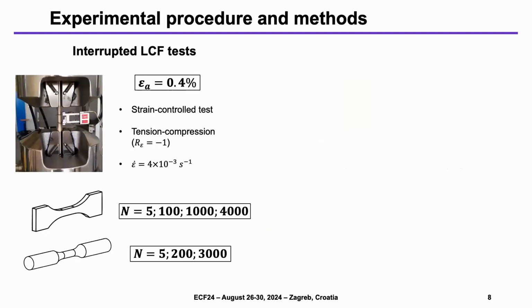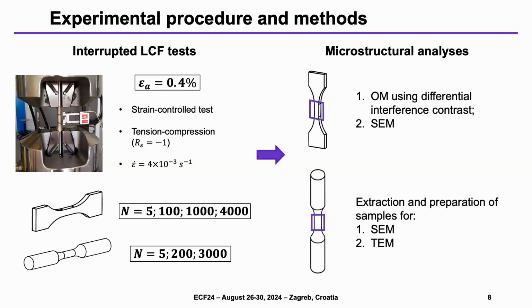Of course, both the flat and cylindrical specimens were then tested in strain control at 0.4% strain amplitude. And as I said at the beginning, the tests were stopped at preset numbers of cycles up to 4,000. Then we observed the surface of the flat specimens, at first using optical microscopy and then using SEM. And then we also extracted some samples from the cylindrical specimens, which were then analyzed by SEM and TEM.